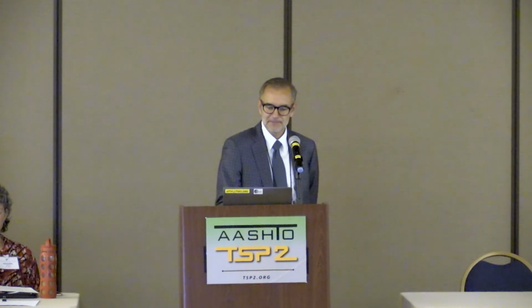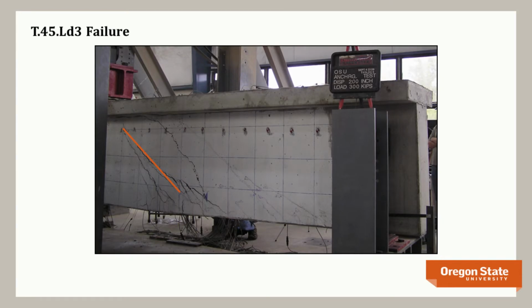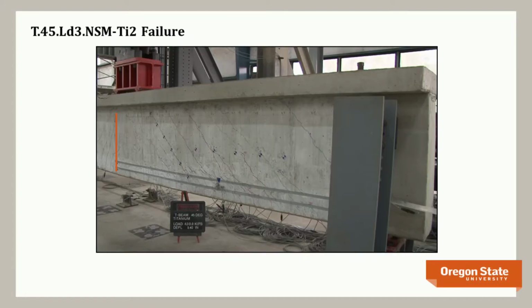Here's a control specimen, all right, and what we've done there, the flexural bar cutoff is here, and all these cracks that you see is that bar inside slipping, which leads to failure. So it's a kind of a tension anchor failure. And this is the same girder. You can see the titanium here added on the sides. Same cutoff location. In fact, we made it harder. We made the development length 1/3 instead of a half to even make the titanium work better.